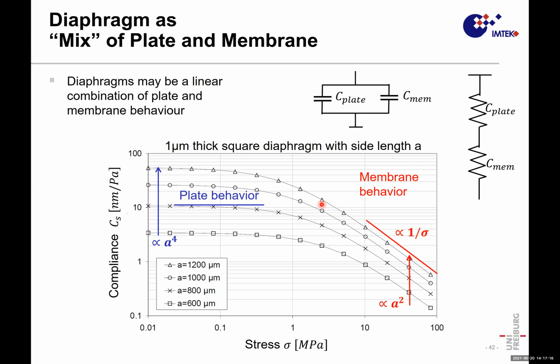Typically it is not easy to come into this range of stresses. Typically we are in this range of 10 to 100 megapascal, and then we can control quite well, but never completely give up the compliance of the plate.